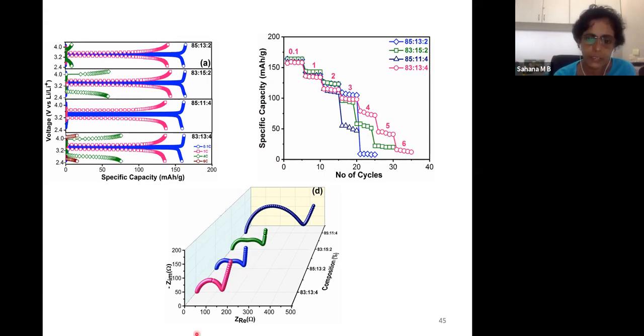The reason for that is the interface impedance between various parts. As I told you, there are a large number of interfaces in a cell. Here what we have focused on is the charge transfer between the active material and the active material. What is the resistance? What is the impedance for the charge transfer? The charge here is lithium ion and the electron, which takes place from the electrolyte and the carbon black to the active material. You can see here this point, the extrapolated first semicircle of an impedance spectra. It keeps increasing with the lower carbon content. You can see here it's very high. The charge transfer resistance is very high, which is not good because we need the charge transfer resistance to be as low as possible.